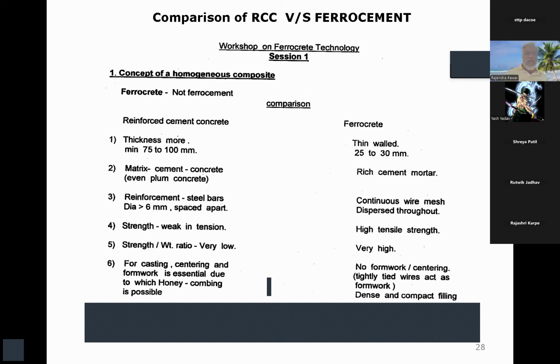That's all. The matrix here, in RCC, is cement concrete. There is even plum concrete up to 100 mm, or 300 mm boulders are also used. Here, it's only rich cement mortar without any coarse aggregate. The reinforcement in RCC is steel bars having diameter more than 6 mm and more widely spaced apart. But here there are continuous wire meshes dispersed throughout the surface area of that particular component in that shape, and that's how it gives strength. And the strength can also be achieved through shapes, giving shapes to that component, and it saves the material cost.